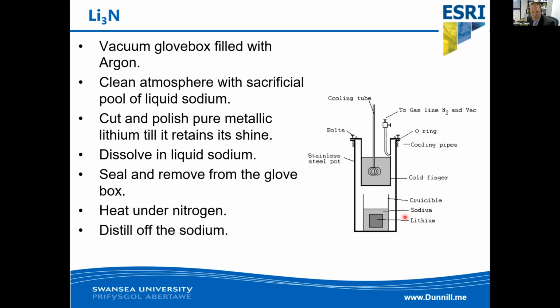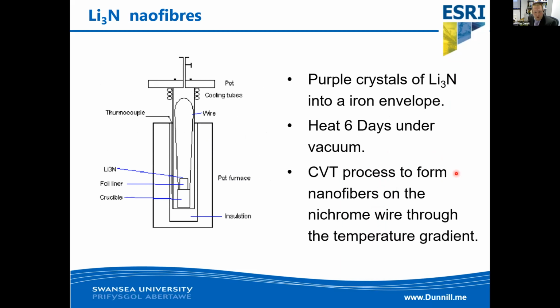The lithium reacts with the nitrogen to form lithium nitride. The liquid sodium keeps the atmosphere nice and clean and gets rid of any oxygen contamination. And then finally, you can use the cold finger here to distill off the sodium. It's a great experiment, great fun if you like liquid metals, but an absolute pain to do. Anyway, once you have your purple crystals of lithium nitride, you can put them into an iron foil liner inside yet another pot.